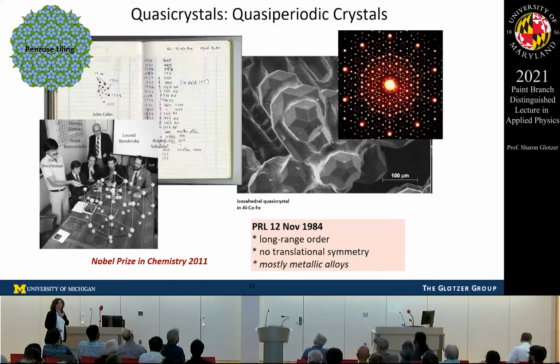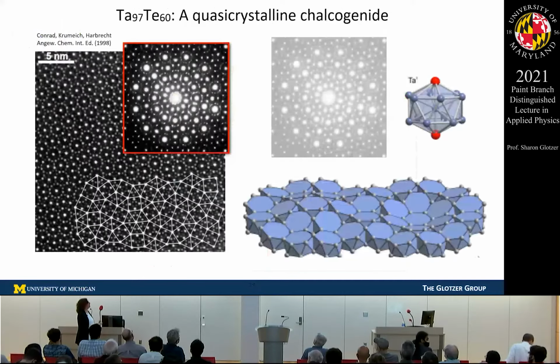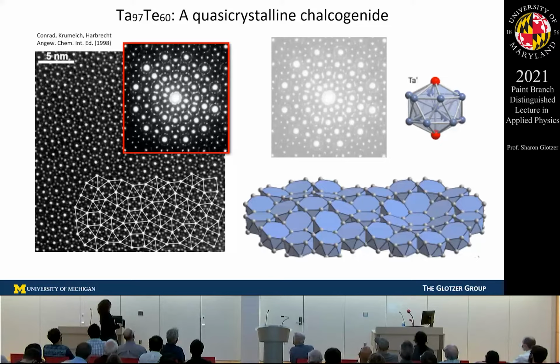The quasicrystal that Amir found, this dodecagonal quasicrystal, turns out to be isostructural to a tantalum-tellurium chalcogenide quasicrystal that had been reported in 1998, I think. Yeah, in 1998. So this is an electron microscopy image of the system of all the atoms. This is a 5 nanometer scale bar. This is the scattering pattern.